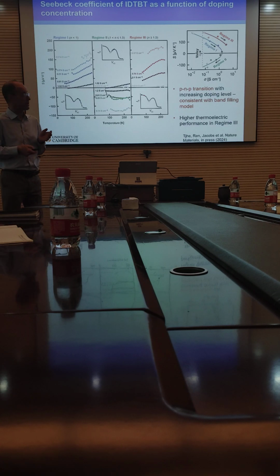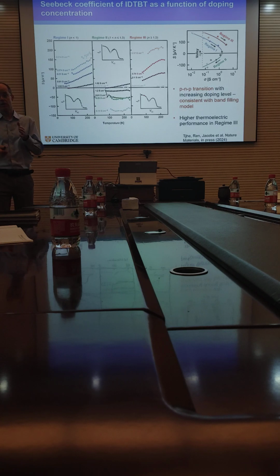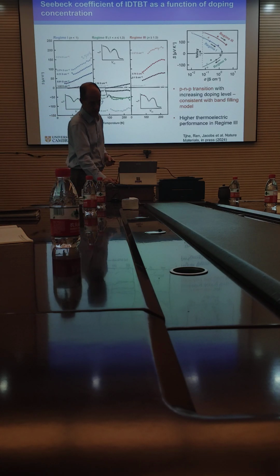So we have a p-n-p transition in the Seebeck coefficient. And that's exactly what you would expect with this band filling interpretation, because in this regime 1, you're dominated by holes at the top of the HOMO level. In regime 2, you are dominated by the remaining electrons at the bottom of the HOMO level. And in regime 3, you are dominated by holes at the top of the HOMO -1 band. So this Seebeck is very consistent with this simple band filling picture.